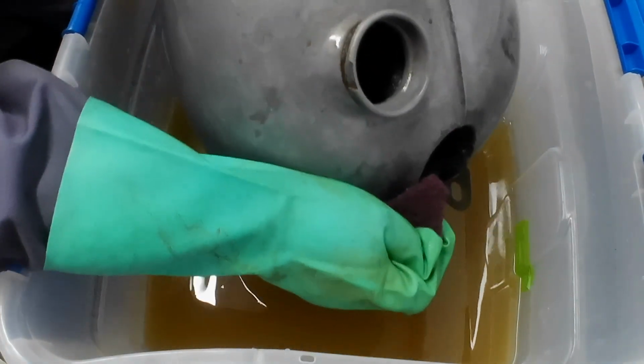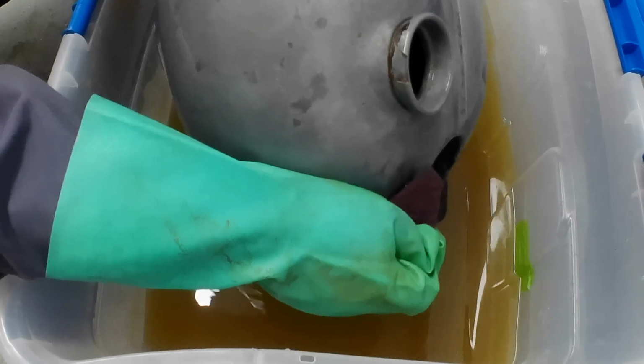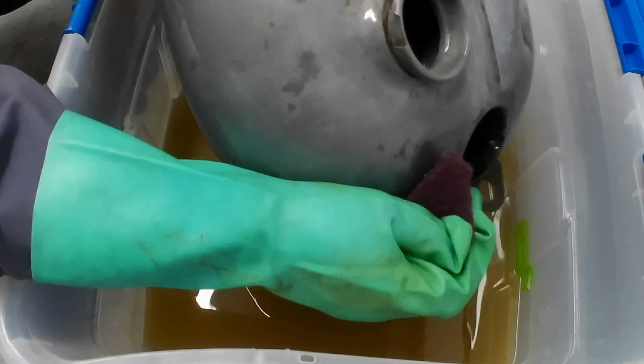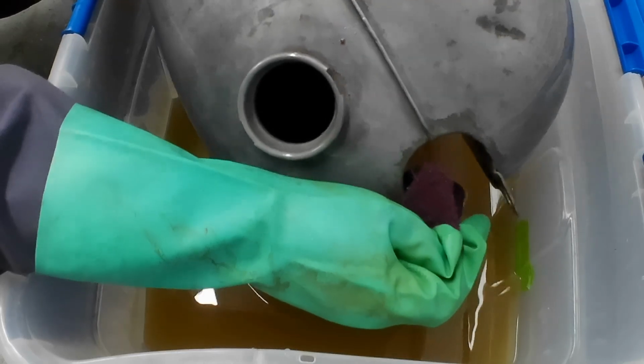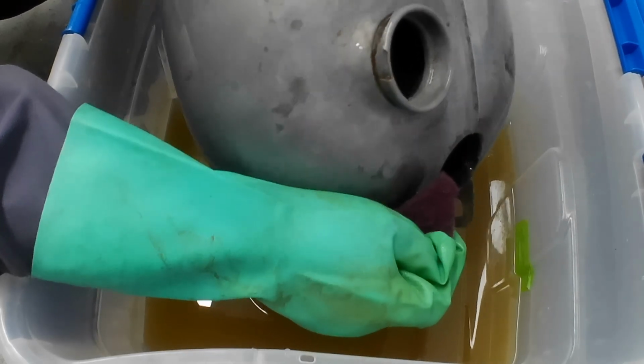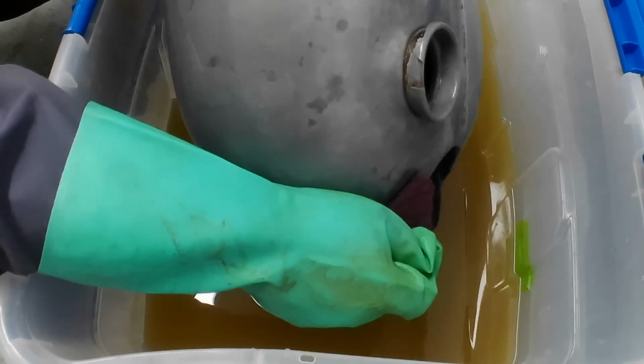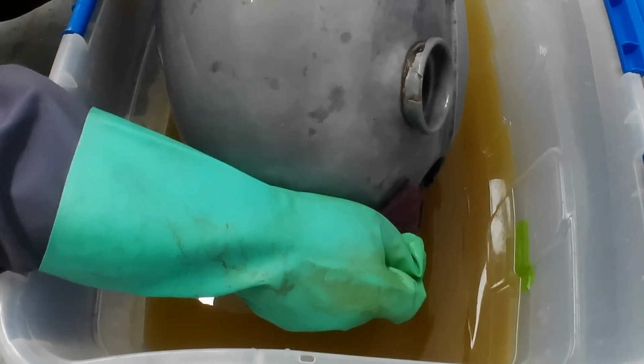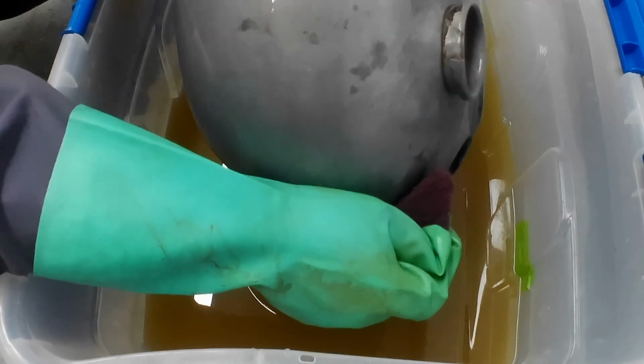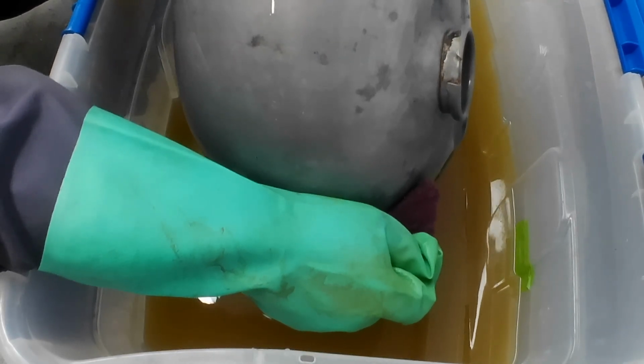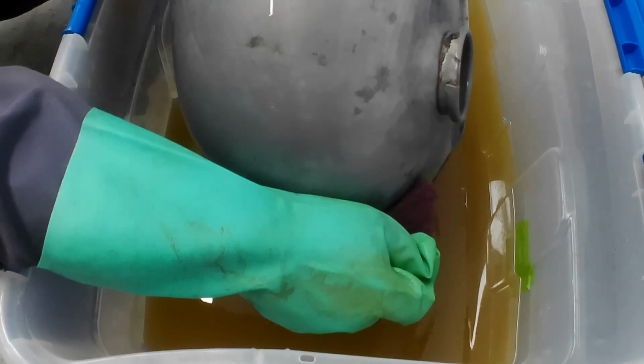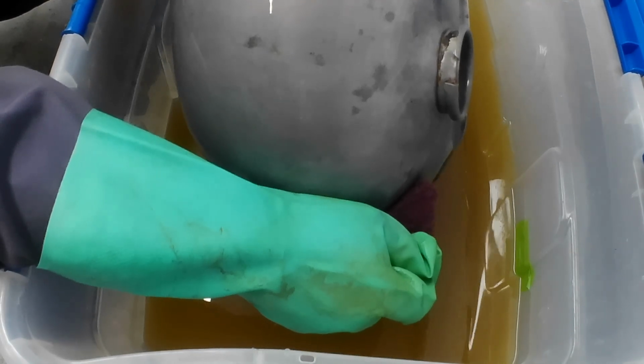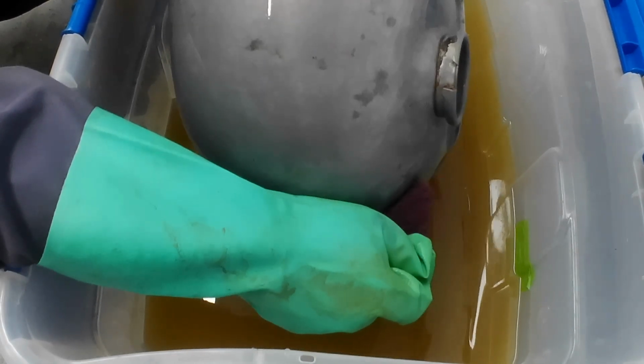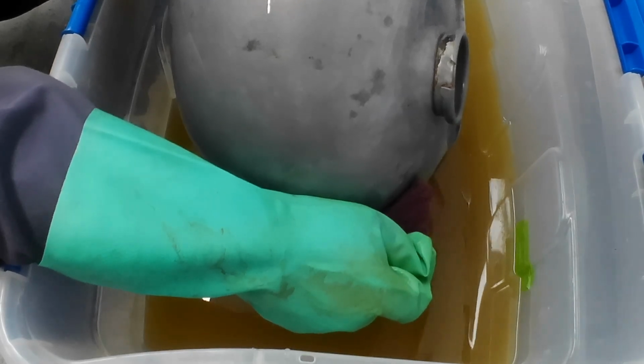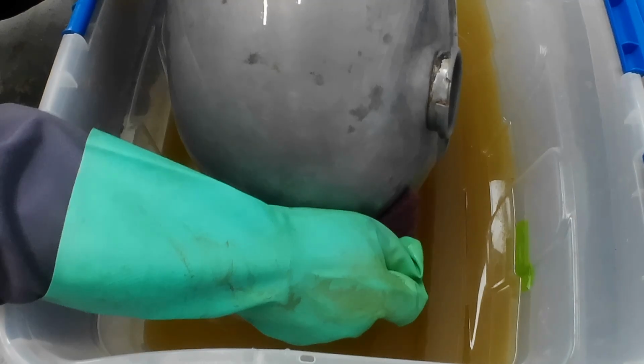Now, you recall me talking about hydrogen being bubbled through the water. At such a low concentration, I'm not worried about anything like hydrogen embrittlement, and the fact that it's a non-structural component is probably a fairly low-grade steel. I'm not really worried about hydrogen. Hydrogen embrittlement is when hydrogen atoms actually work their way into the lattice of the steel, due to the fact that they're very small, and there's quite reasonably large gaps in the lattice that makes up steel, and the hydrogen can actually infiltrate.